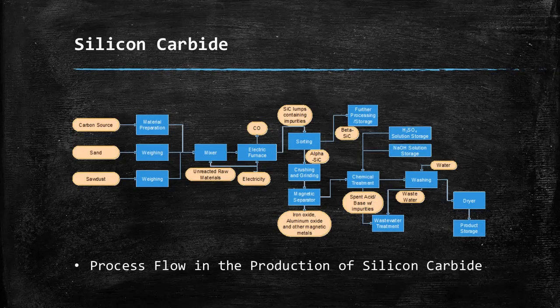The production of silicon carbide starts with a mixing of high-grade raw materials. Sawdust is occasionally added to reduce mixture's density and increase its porosity. High porosity is needed in order to enhance the removal of carbon monoxide and other volatile compounds in the silicon carbide layers formed during the reaction. After blending the appropriate raw materials, the mixture is loaded in an indirect batch-type electric resistance furnace. The furnace consists of a graphite electrode installed at the center. Resistance furnace is chosen because it facilitates the formation of layers, aiding the separation of silicon carbide from the unreacted mix.